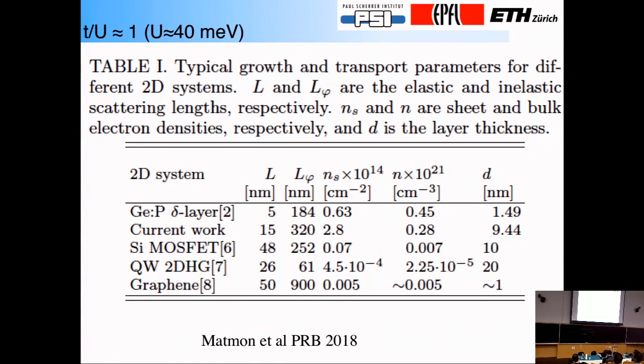So now that I have this ability to build these structures, we could actually go back and think, well, can we build a Hubbard model on a particular lattice? And so if we can place the phosphorus atoms, for example, in well-defined locations, then literally we can make a Hubbard model that we can then control, let's say, hopefully optically, and also measure electrically. We can, of course, vary the lattice constants at will and look at phase diagrams. Essentially do all of the very pretty physics in the same way that the atomic physicists are looking at their version of the Hubbard model.